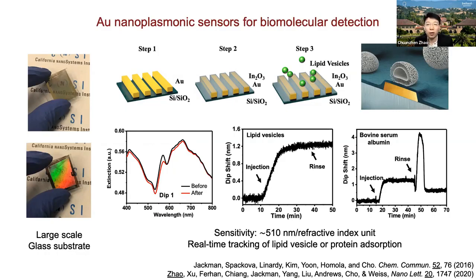Moreover, we use this for sensing of biomolecules, including proteins and lipid vesicles. Here we coated the surface with a nanometer-thin indium oxide to study the adsorption and desorption of those molecules on the metal oxide surface. For example, we were able to track the plasmonic peak upon the adsorption and desorption of lipid vesicles and also BSA on the oxide surface in real time. Other plasmonic sensors can also be fabricated by functionalizing the oxide surface with different receptors, such as antibodies.